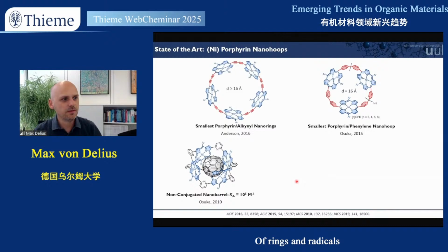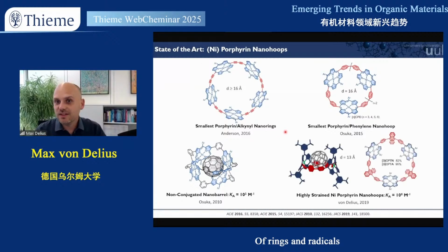So here we are in a research community about putting porphyrins into rings. And in 2019, we reported the smallest and most strained cycloparaphenylene porphyrin hybrid macrocycle. And we observed some very interesting redshift in the UV spectrum. We saw that only nickel porphyrins actually survive this crazy strain energy of 50 kilocalorie per mole. And we used this to bind fullerenes, our favorite guest. We also made bigger ones, but we didn't really care about them at the time.